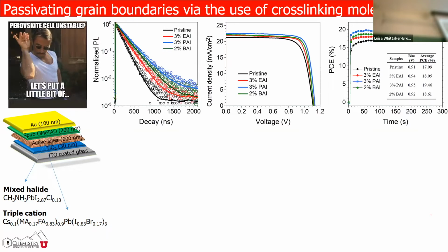So we actually did time resolved photoluminescence to look at carrier lifetimes. So we know that we have an increase in the carrier lifetime when we go to the 3% propyl ammonium iodide, right? So it means that the recombination paths for these materials are lower. So then if we actually look at the IV curve, here I have my short circuit current, so the current that I'm generating at voltage equals 0. Then here I have my VOC, so open circuit voltage, the voltage that I'm generating at current equals 0.